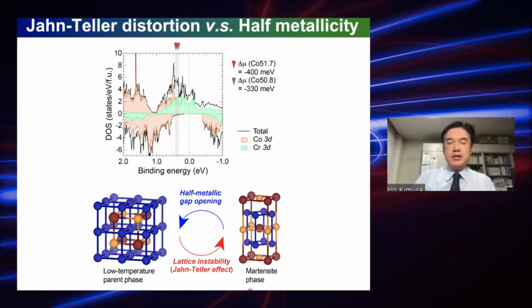So now I'm going to summarize our discussion. Now we compared the cobalt-rich and the cobalt-poor samples. Now we know that the Fermi energy position is higher for the cobalt-poor sample. And the cobalt-rich sample has a Fermi energy position near the peak of the density of states in the majority spin channel. By the way, the stoichiometric composition locates the Fermi energy near this density of states, not far from the peak of the density of states in the majority spin channel, which means off-stoichiometry maybe drives the lattice instability. Actually, the cobalt-rich sample maybe has the Fermi energy closest to the peak of the density of states, which may be the reason why you have a lattice instability.